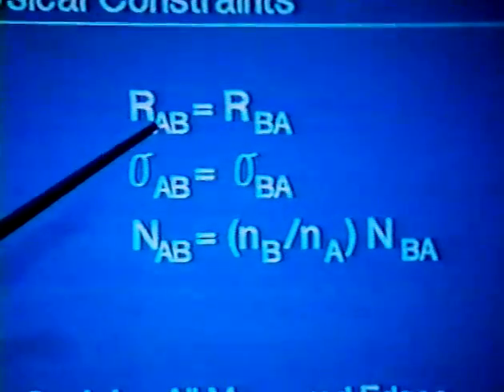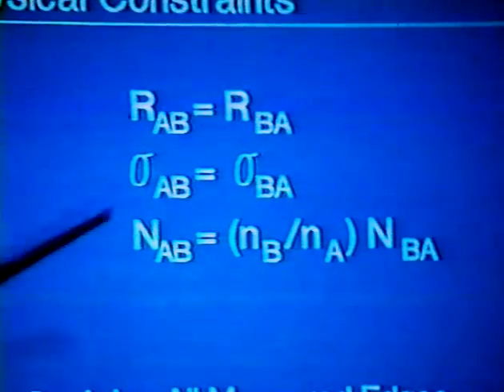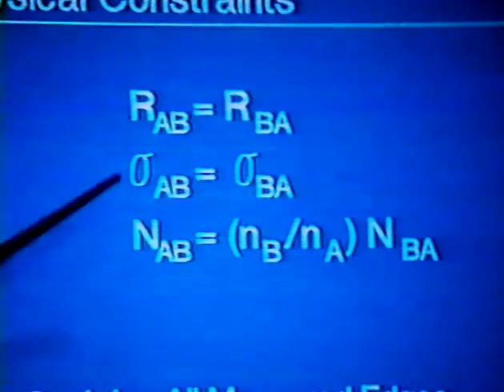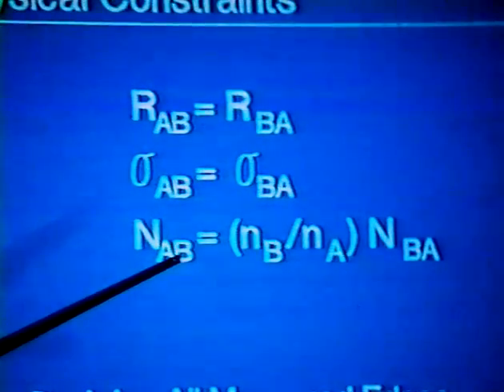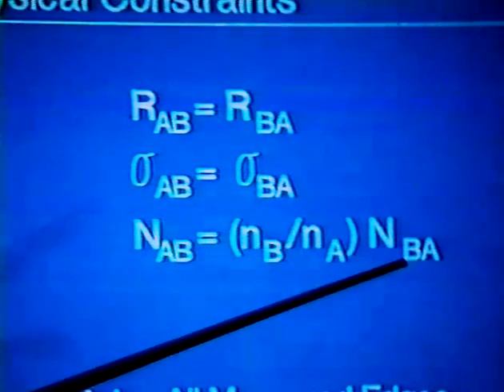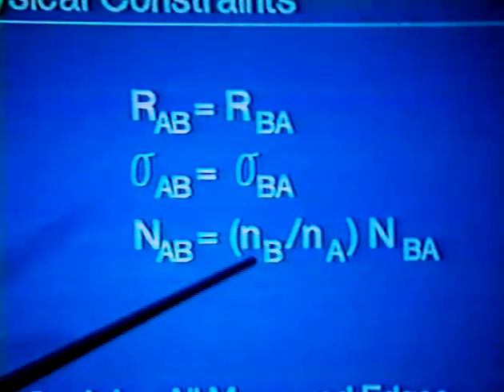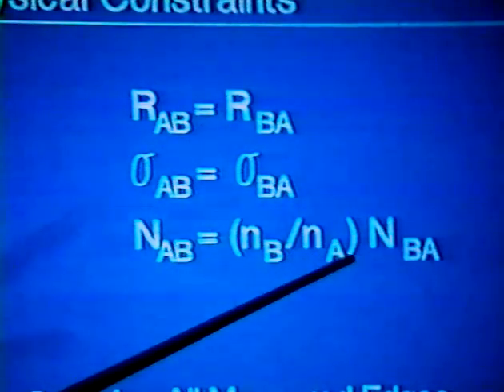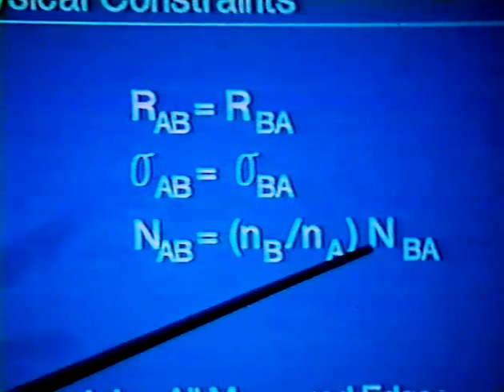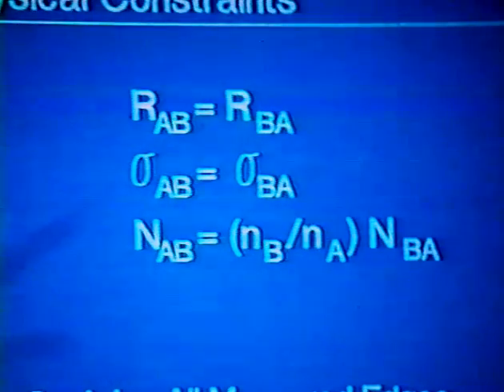Similarly, the mean square relative displacement about the distance, determined from the A-type atom, and the displacement determined from the B-type atom, also has to be equal because they're looking at the same bond. And finally, the coordination of atoms of type A by atoms of type B, it turns out, is equal to the coordination of atoms of type B by atoms of type A, subject to a factor which takes into account the atomic ratio of these two types of atoms in the sample. This last condition is equivalent to saying that if I have 6 neighbors, then 6 people also have me for a neighbor. So that when you take into account the number of different people we're talking about, we've got 1 here equals 1, or 6 here equals 6. So the value of this type of thing is that when we're analyzing 2 spectra, we're reducing the number of variables, and we're improving the information because we're putting in new information which is not model dependent.